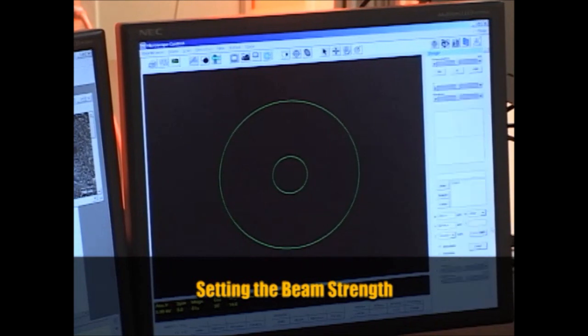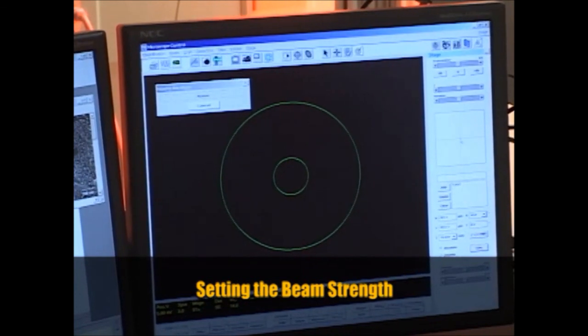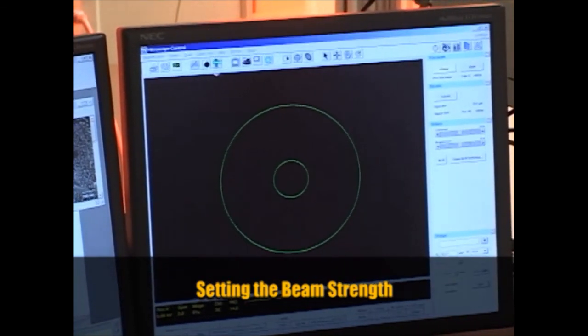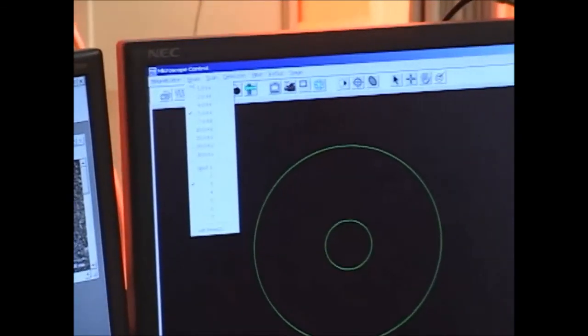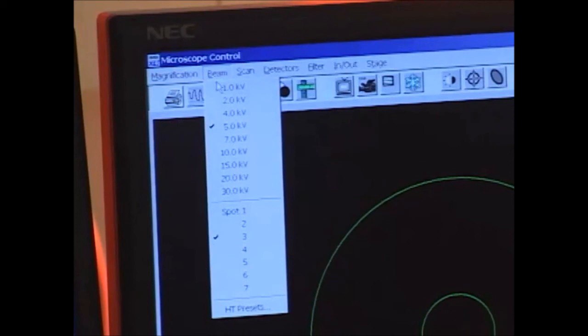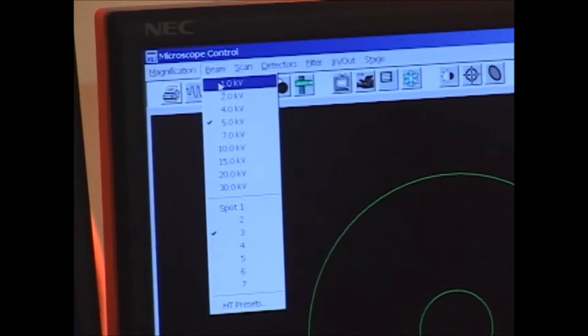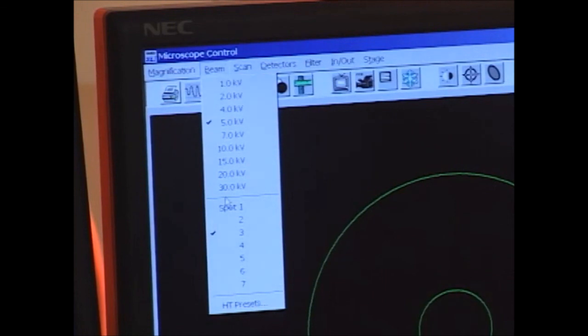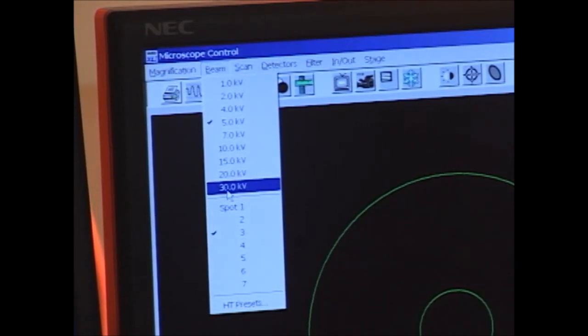While the chamber is pumping down, you can do 2 things. The first is you want to center the sample on the stage. And the second thing you want to do is set the beam conditions that you're going to use to image the sample. The first menu here is accelerating voltage, which can go anywhere from 1.0 keV to 30 keV. Lower accelerating voltages are good for fragile samples like biological samples. Higher accelerating voltages give you better resolution. So any sample that conducts well enough to tolerate the high accelerating voltage, 30 keV or 20 keV, you want to use that because it will give you a better image in the end.